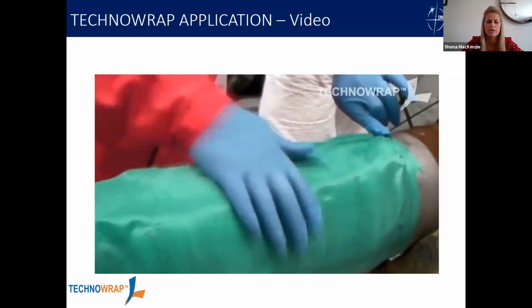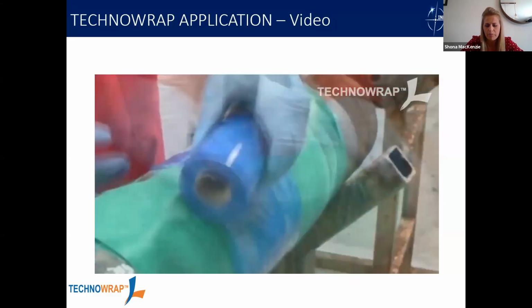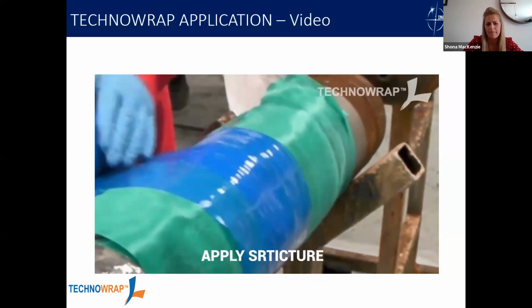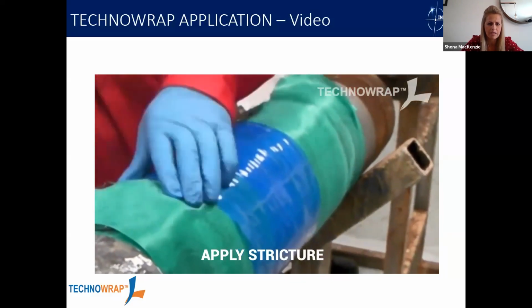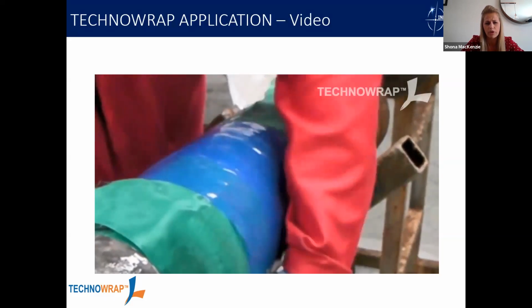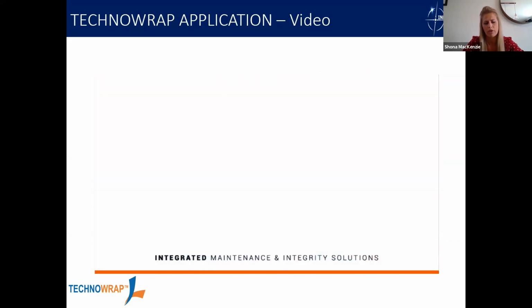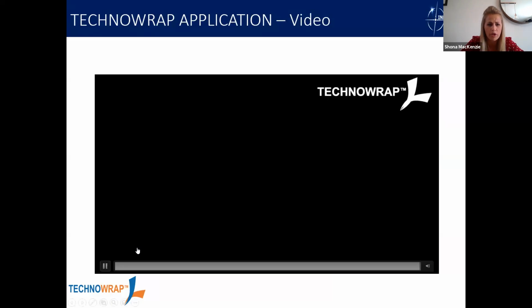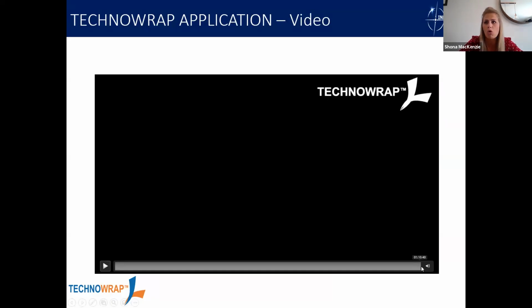of the next layers. What we then do is we apply over the top of that the stricture, and this is applied from the middle, and we work that all the way along the composite itself, and that pushes out any of the additional resin system that's not required, and it removes any air pockets that might be within the composite itself.